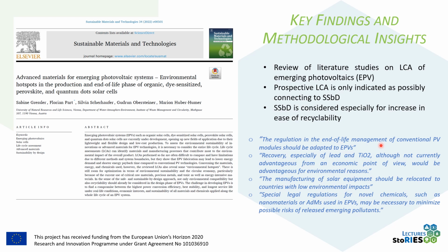life management of conventional photovoltaics should be expanded and adapted to the emerging photovoltaic system; that recovery of the materials, especially lead and titanium dioxide, would be advantageous for environmental reasons, although presently it is not advantageous yet. And third, the manufacturing of solar equipment possibly should be relocated to countries with a lower environmental impact.